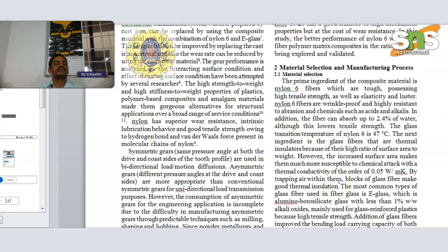On material selection and the manufacturing process, the prime ingredients of the polymer composite material are nylon 6 fibers, which are tough, possessing high strength and elasticity and luster, wrinkle proof, and highly resistant to abrasion and chemicals such as acids and alkalis. In addition, the fiber can absorb 2.4% of water, although it has lower tensile strength. The glass transition temperature of nylon 6 is 47 degrees Celsius. The next ingredient, glass fibers, are thermal insulators because they have a high surface area to weight ratio. However, with increasing surface area they are much more susceptible to chemical attack, with a thermal conductivity of the order of 0.05 W/mK by trapping air within them. The blocks of glass fibers make good thermal insulation.